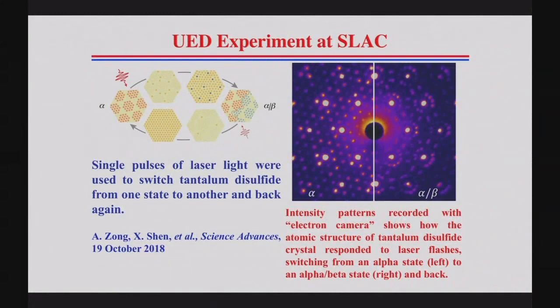And so this experiment was done last year. What they did was they took the material, and they just sent one pulse of laser light, a single pulse. When you send a single pulse, it starts a reaction where the pristine structure, which is called alpha over here, begins to transform, and it forms 2 different structures in the same material, alpha and beta, and there is a wall between them, a boundary, which is called a domain wall. And it is the motion of the domain wall they were able to monitor through this UED facility.